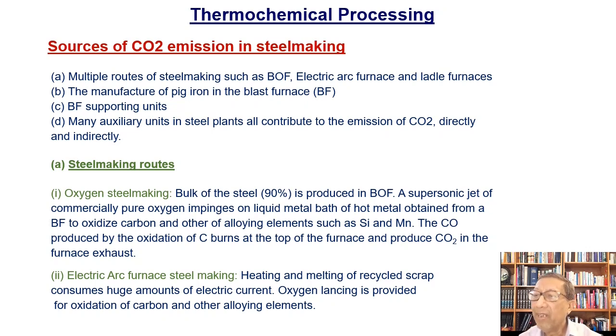So what are the steelmaking routes? Let's review. Oxygen steelmaking, right? Where we take an oxygen lance and we supply oxygen in a basic oxygen furnace at a rate of about 18,000 standard cubic feet every minute in the form of a supersonic jet of commercially pure oxygen, and impinge that on hot metal obtained from the blast furnace to oxidize the carbon, right? And other alloying elements such as silicon and manganese. The carbon monoxide that we produce by oxidation of carbon burns at the top of the furnace and produces carbon dioxide in the furnace exhaust.